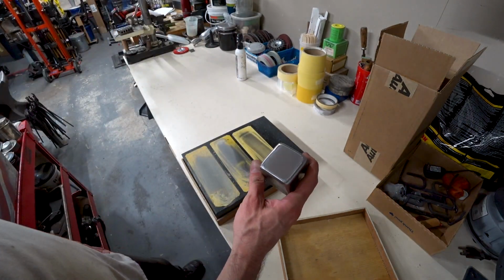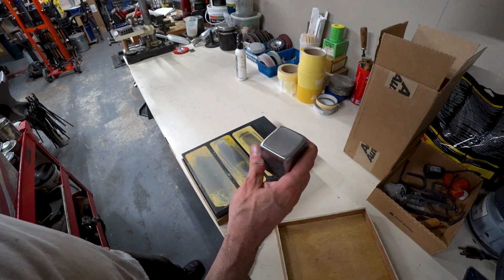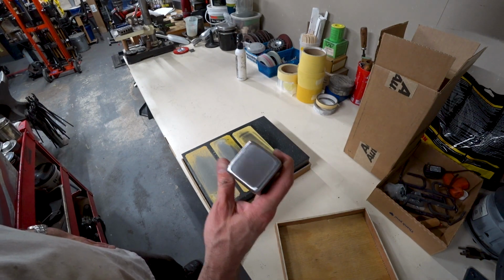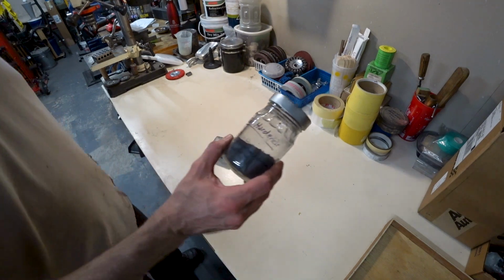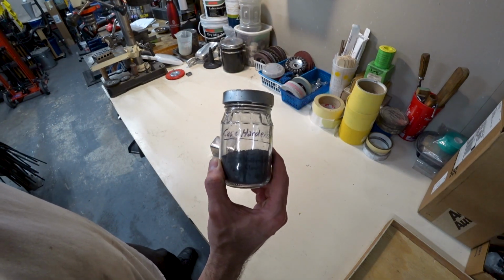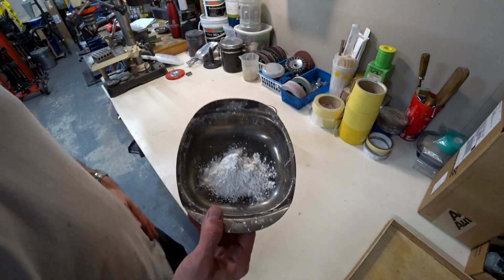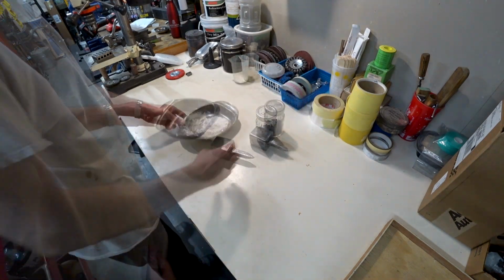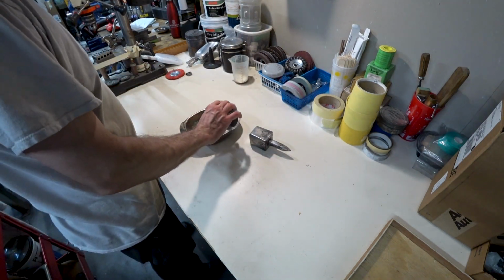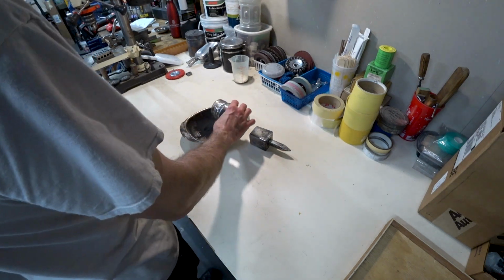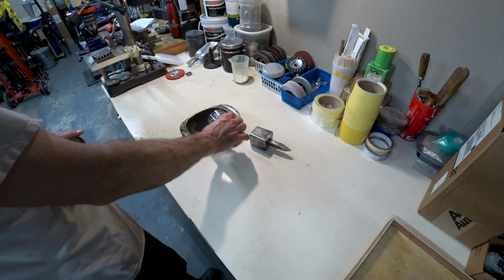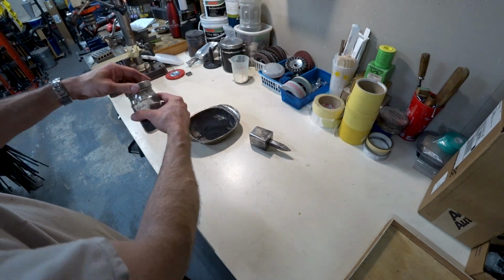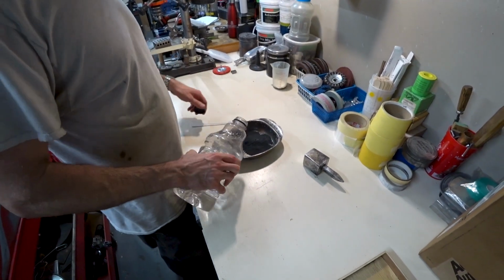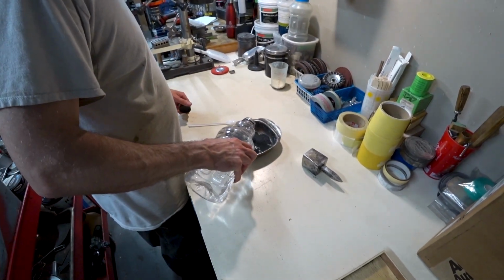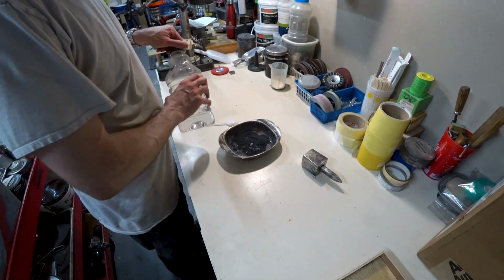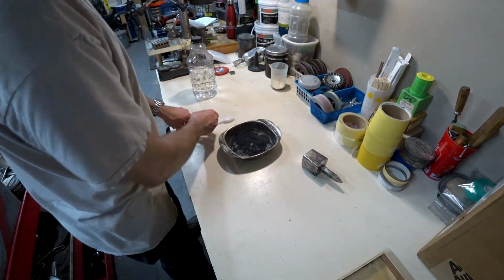There are some commercially available products like Kasenit, but they're hard to get, they're expensive, and they have some harsh chemicals in them that we don't need to use. The homemade compound that I use just has about 20% sodium carbonate, and the rest is crushed charcoal. We'll use regular white flour as the binder. I use a ratio of about 2-to-1 compound to flour, but it's not critical because the flour is mostly carbon as well. I mix the compound and flour before adding water, then add just enough water to form a dry paste and mix thoroughly. What you end up with is a bit like Play-Doh.